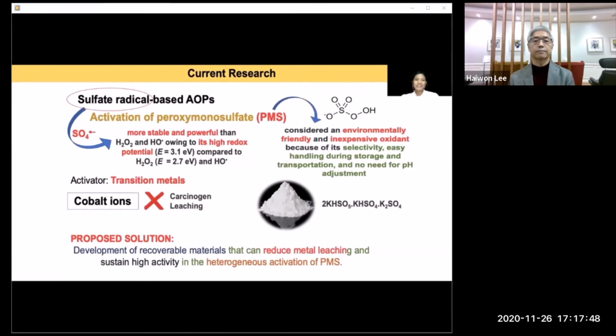For sulfate radical-based AOPs, cobalt ions are considered the most efficient in terms of activating peroxymonosulfate. This PMS is considered an environment-friendly and inexpensive oxidant because of its selectivity, easy handling during storage and transportation, and there is no need for pH adjustment when this material is used. However, when we are using cobalt ions, issues of leaching and non-recyclability hamper the use of these ions. These ions are considered carcinogenic.